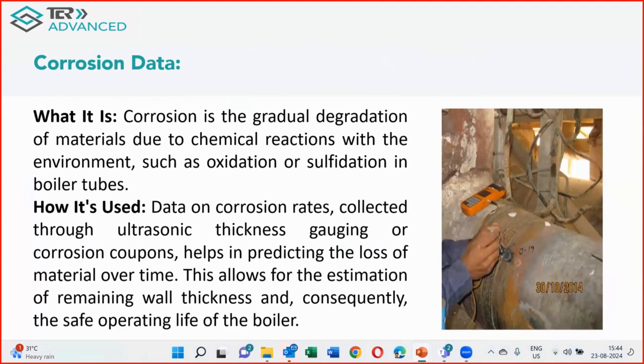So what is corrosion? Corrosion is the gradual degradation of the material due to chemical reaction with the environment, such as oxidation, sulfidation. It happens in the boiler tubes. So basically, overall thickness loss occurs. But what about the loss of thickness which occurs in a localized way? This is very dangerous. So it is also called corrosion. Design is done for general corrosion and not localized corrosion. So this is the data interpretation which we need to understand. And an extensive thickness survey is the only answer to identify this issue.